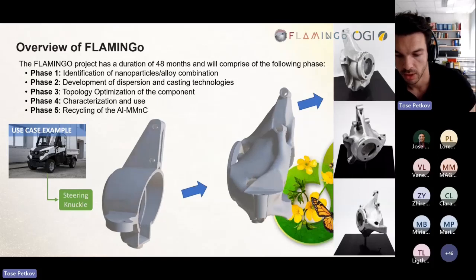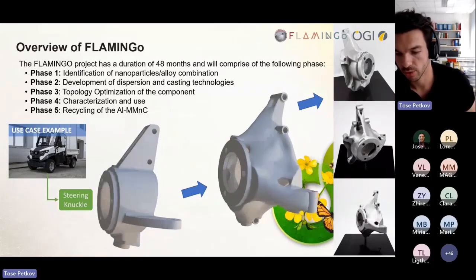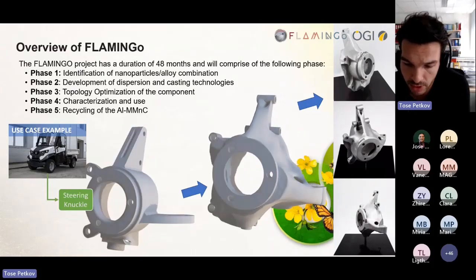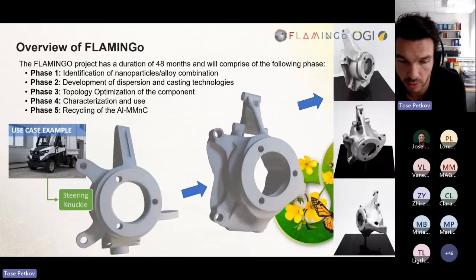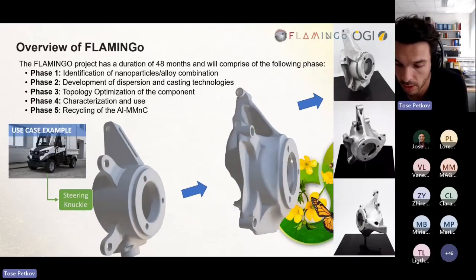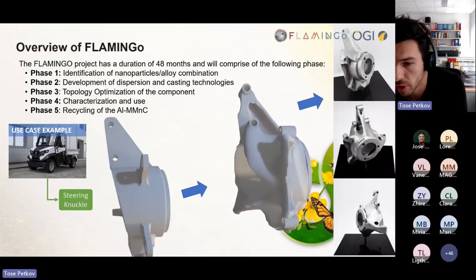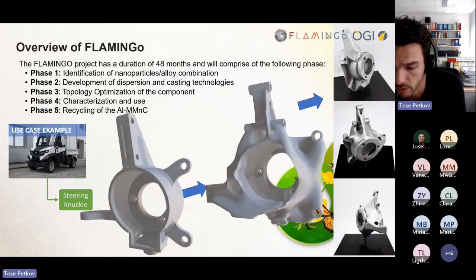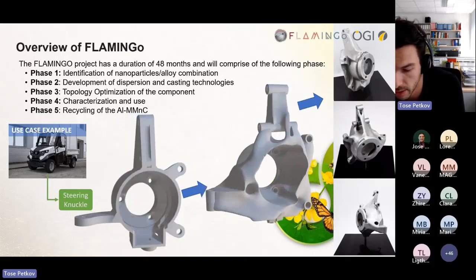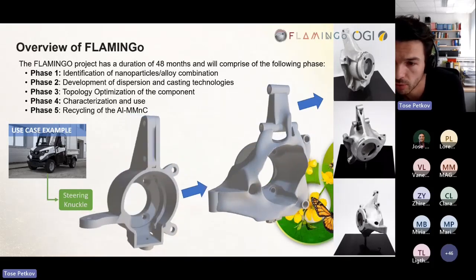So here we see how the component changed from steel to aluminium by topology optimization and nanoparticle reinforced aluminium. We have a totally different shape and geometry. This is not the final product yet. We also did some further improvements to make it more cast stable and easier to produce the sand models, and also later on for the low pressure die casting for the steel molds.